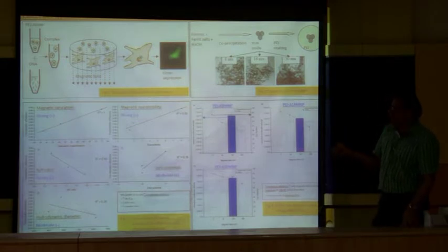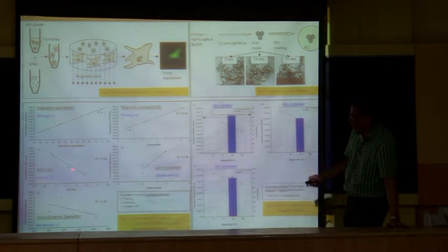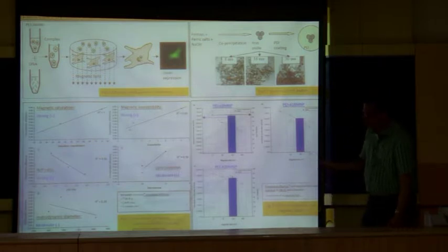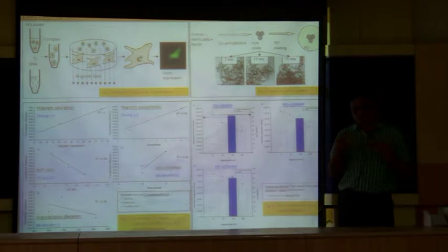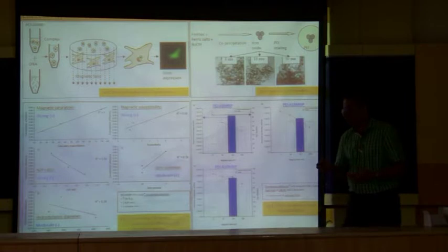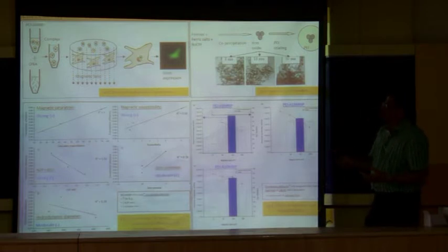And you know when something has been transfected because you can use some kind of a reporter gene and get the gene expression. So we've done this work with a variety of magnetic particles which we have coated with PEI. We have measured the magnetic properties, the susceptibility, and the zeta potential, and we have some results which point to the optimum magnetic particle size, the optimum charge, and the optimum coating thickness in order to effect gene delivery.